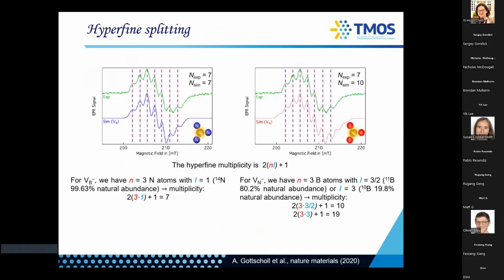And so you can model boron vacancy or nitrogen vacancy, you know it should be something very simple because the whole crystal is basically changing color. So for boron vacancy, negatively charged, you would see 7 lines. Yeah, so basically 3N.